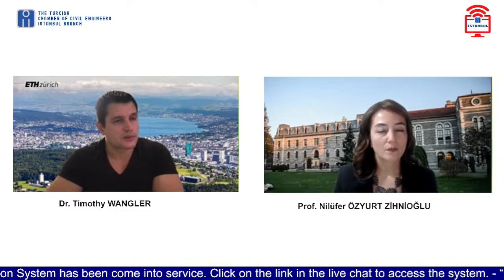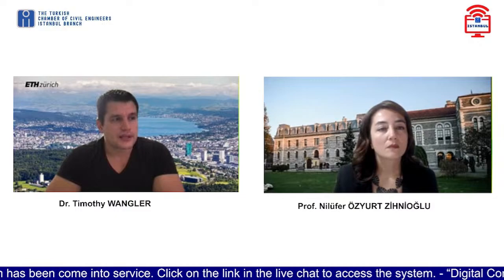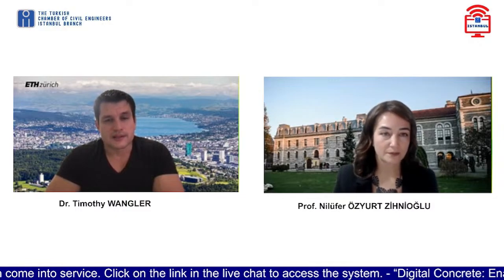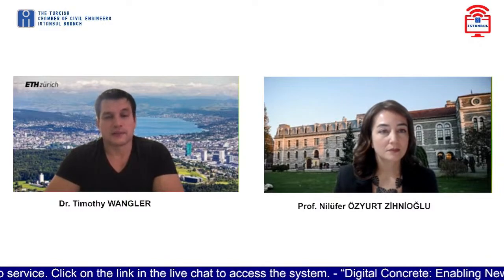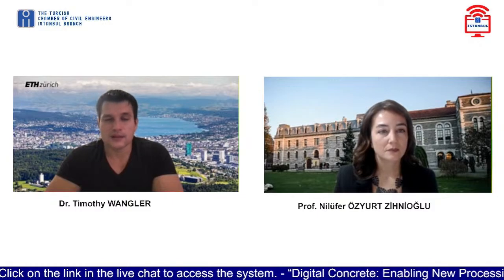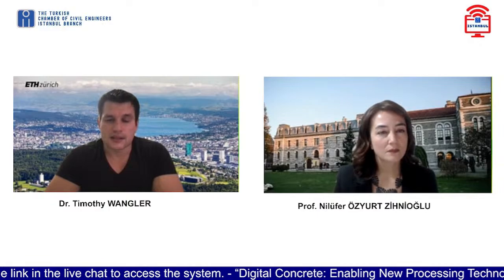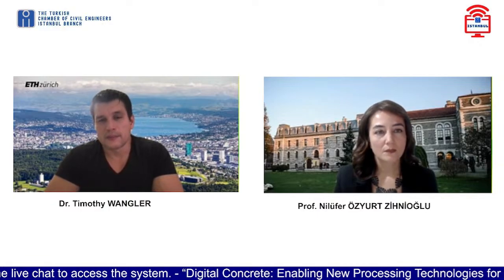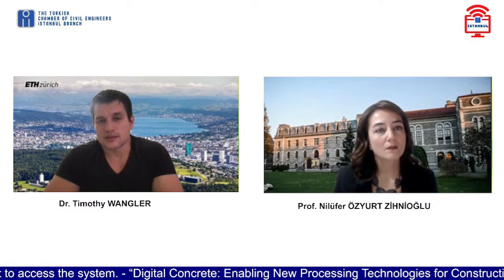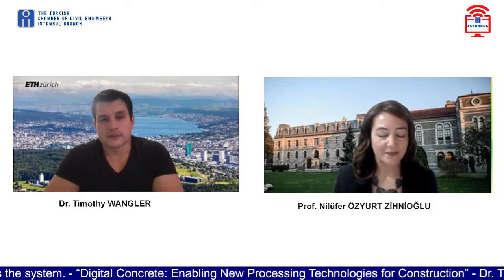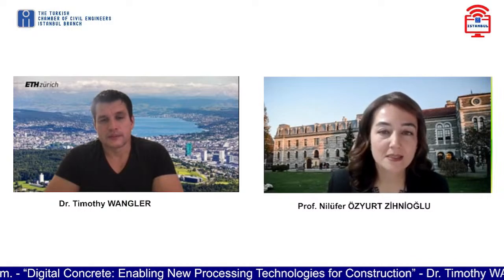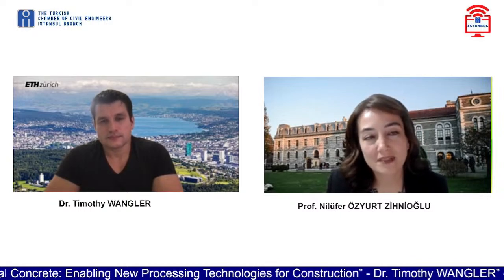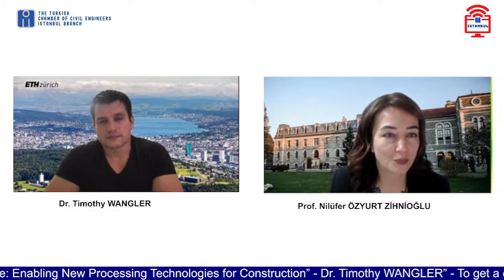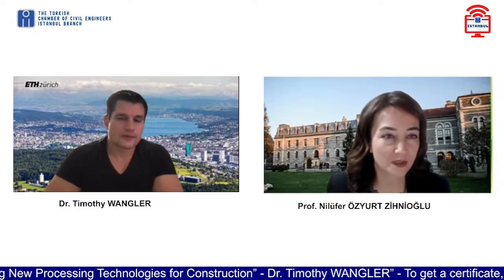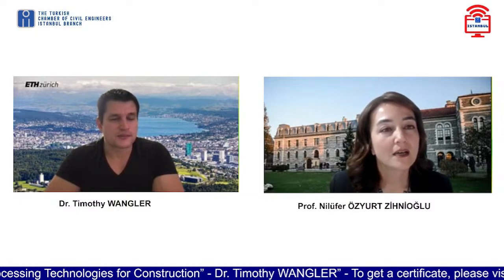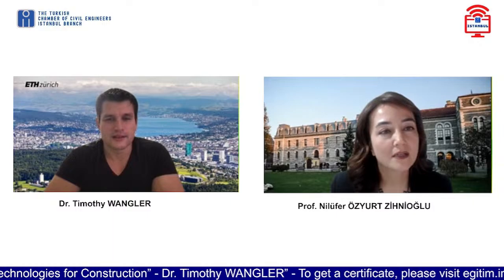The bridge that I showed in one of the first slides from Eindhoven, they tested that on a one-to-one scale. So it's still a very expensive process. I think that the way that many people get around it now, and this is a very wasteful way, is that you just don't consider the 3D printed concrete at all. It's just considered as a lost formwork. That's what I know about this situation, and it's not only expensive, at the same time, very time consuming. You have to wait for maybe months, right, for the permissions, up until you carry out all the experimental procedures. Yeah, and as we are in Switzerland, we also have to even wait for the town, the people, to vote.